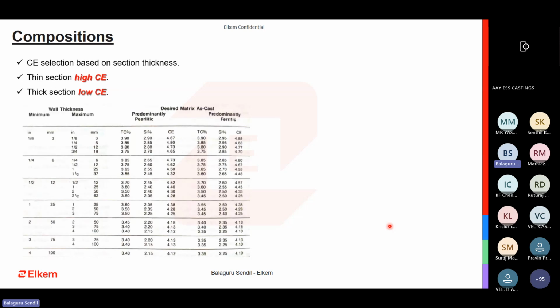The correct carbon equivalent to keep should be based on your section thickness. So thin sections typically go for higher carbon, and then the carbon equivalent is also high. Thick sections, we go for low carbon equivalent.